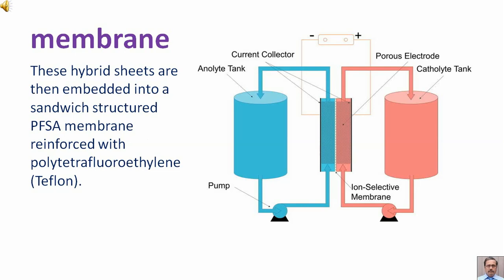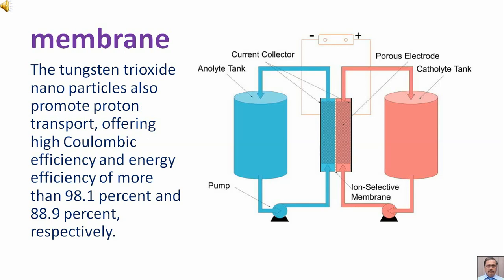These hybrid sheets are then embedded into a sandwich-structured PFSA membrane reinforced with polytetrafluoroethylene, that is Teflon. The tungsten trioxide nanoparticles also promote proton transport, offering high coulombic efficiency and energy efficiency of more than 98.1% and 88.9% respectively.